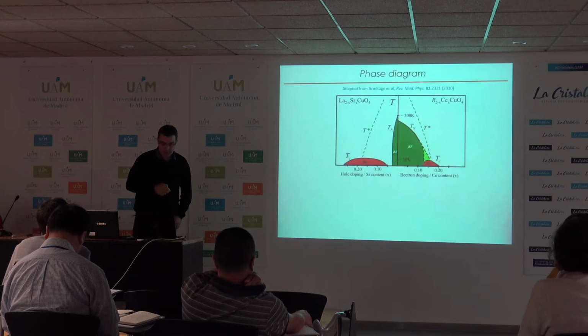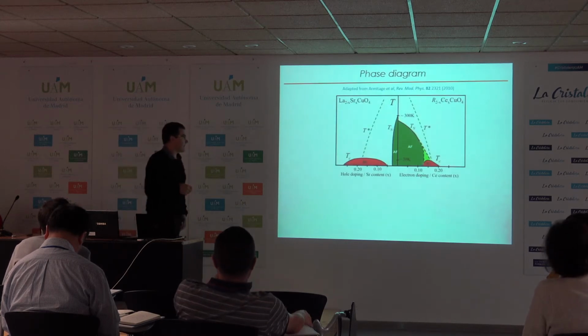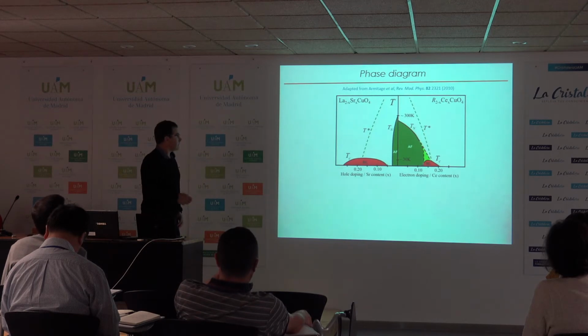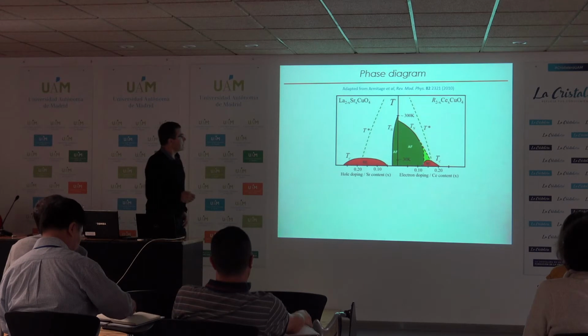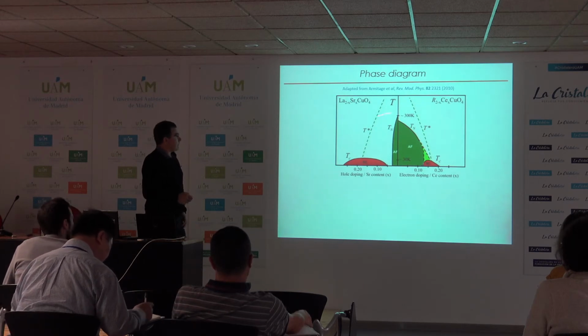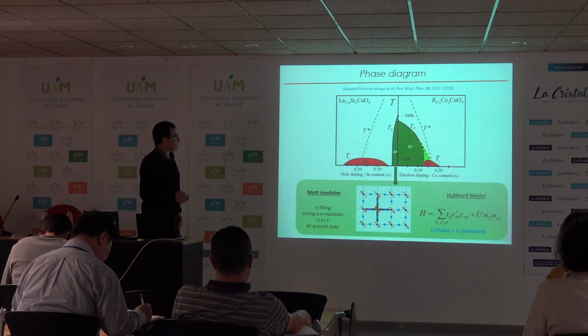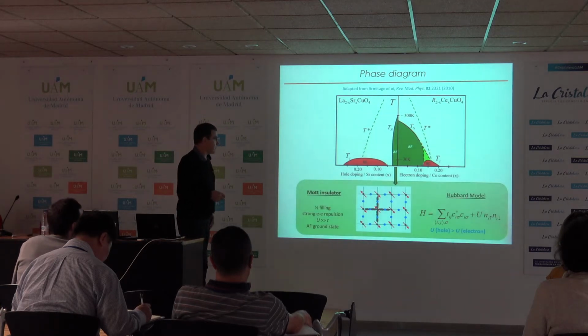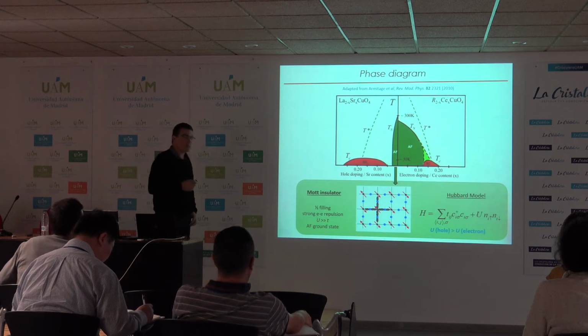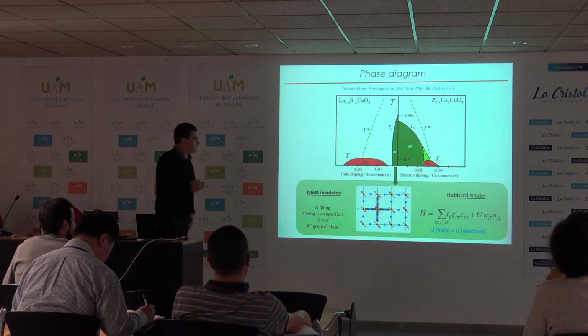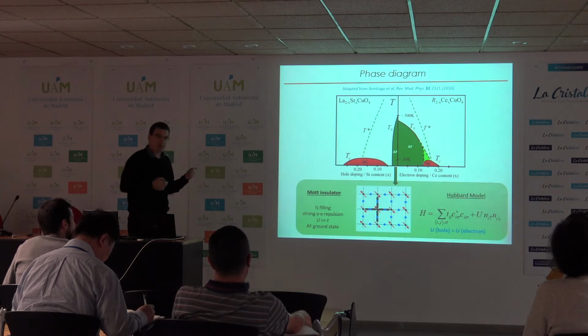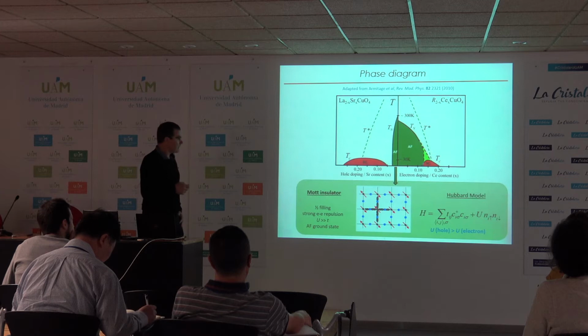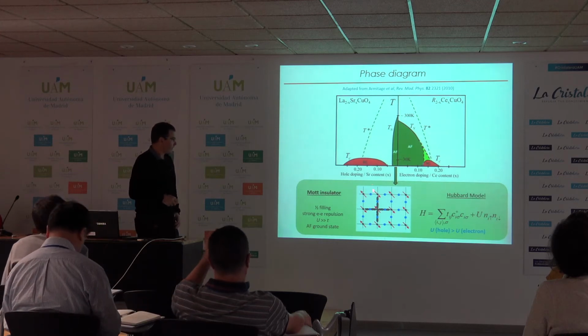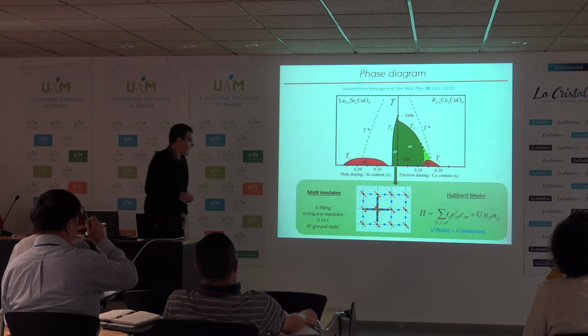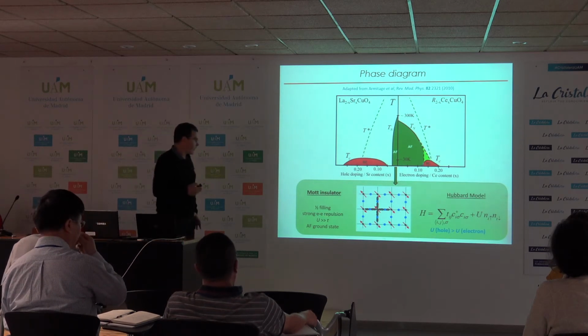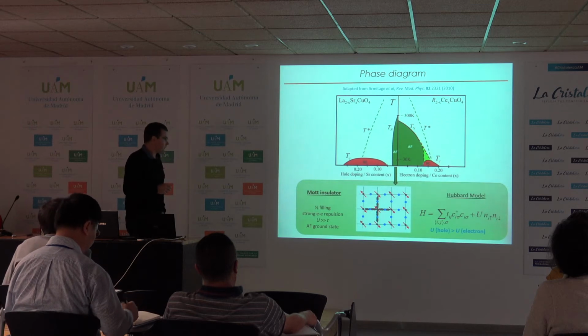Okay, so let me start with the phase diagram. You have seen that several times now. This is temperature, hole doping, electron doping. For both hole and electron doped cuprate, the parent compound is a Mott insulator. Pablo yesterday gave a very good introduction to the subject. Basically, band structure calculation predicts that you have one electron per unit cell, so it's a metal. But due to strong electron-electron correlation, in fact, the electrons are blocked on the copper site, and this is what we call a Mott insulator with an antiferromagnetic ground state.